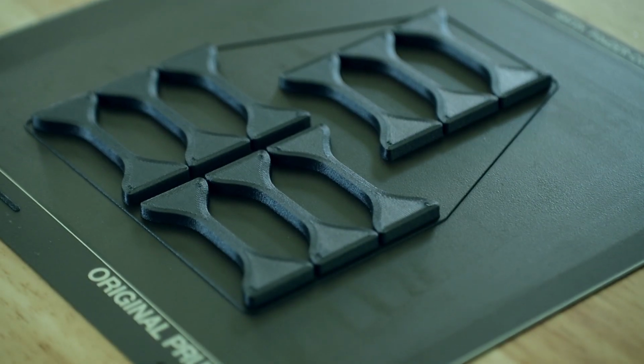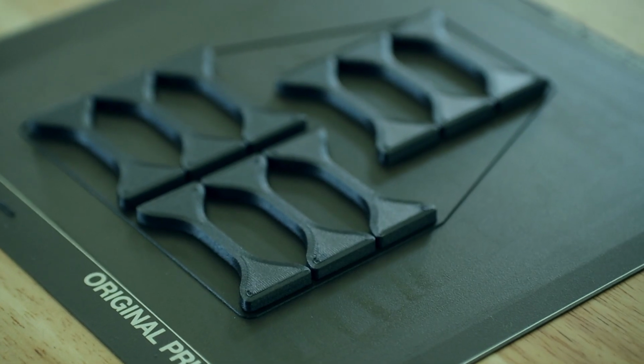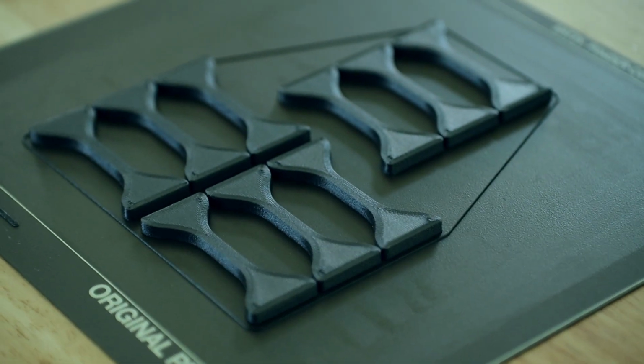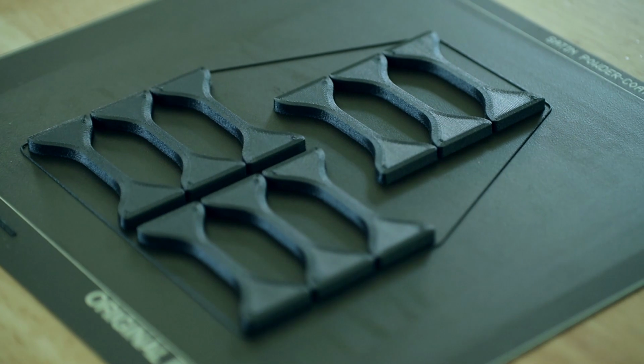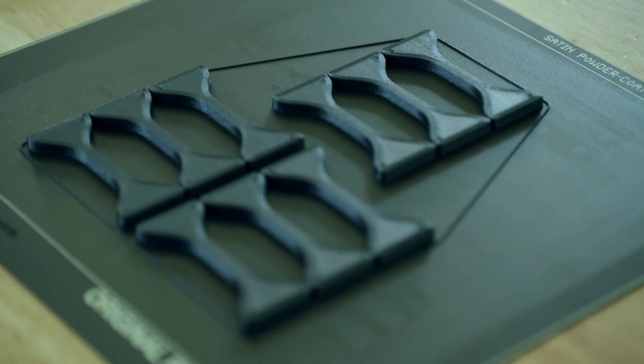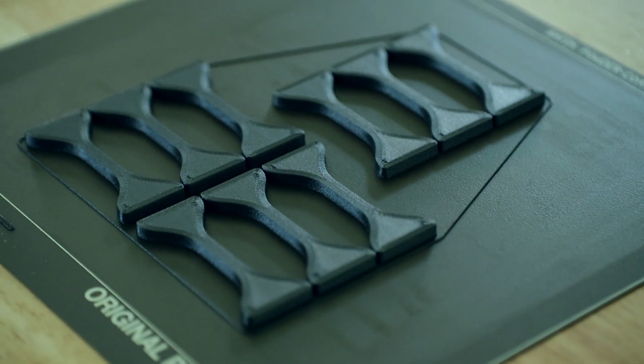Moving forward, what am I going to do next? So first of all, I'm actually going to do the exact same test with the Polymaker PA12 carbon fiber nylon. PA12 is significantly less hygroscopic from everything I've read. Nylon 6 is very hygroscopic. That's what the Taulman Glass Fiber Nylon is based on from everything I can tell. The Nylon 12 should be much stiffer after absorbing moisture. However, Nylon 12 in general is weaker than Nylon 6. It's going to be a super interesting comparison, and I am interested in what the results of that are.